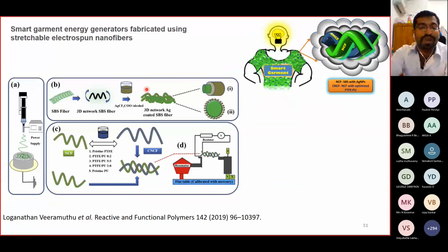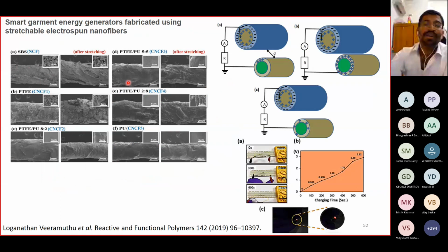And this is another paper we published, and this one is based on some energy generators, textile-based energy generators. And in this case, we are using two different polymers, and we tune them, we optimize the conditions, and then we form the nanofiber-based structures like here. You can see the SEM structures, and then the mechanism is reported here. And we are forming these kind of structures under strain conditions.